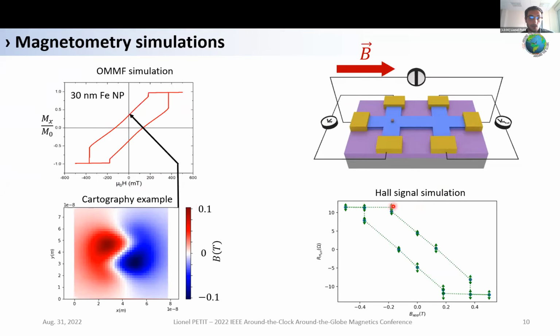And with that, we can retrieve the cycle of the nanoparticle. So it means that this kind of measurement can give access to the shape of the cycle, to coercive fields, to magnetization at remanence. So it's a very promising way to measure a nano object, an individual nano object.